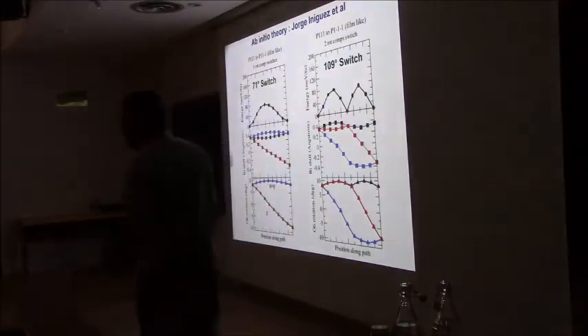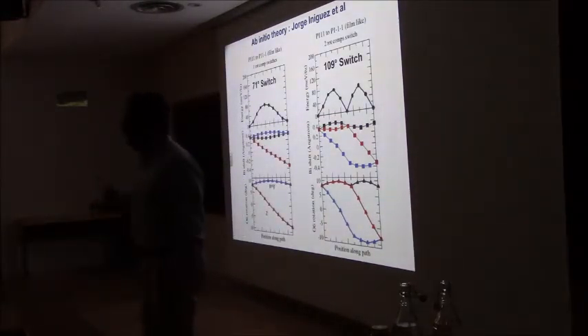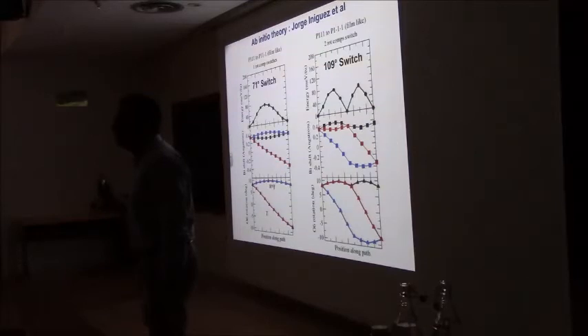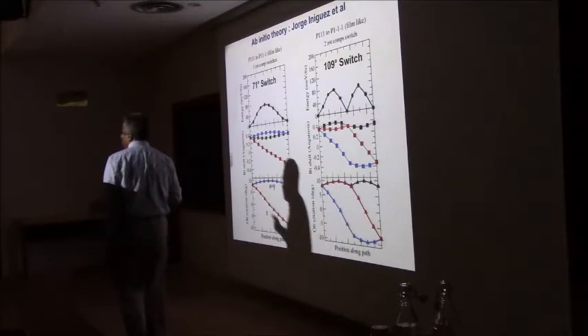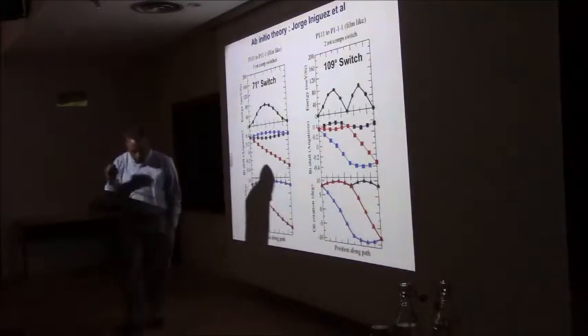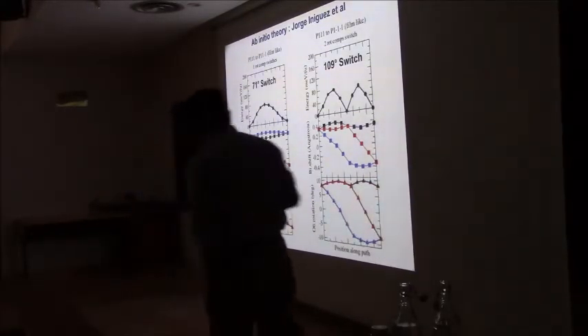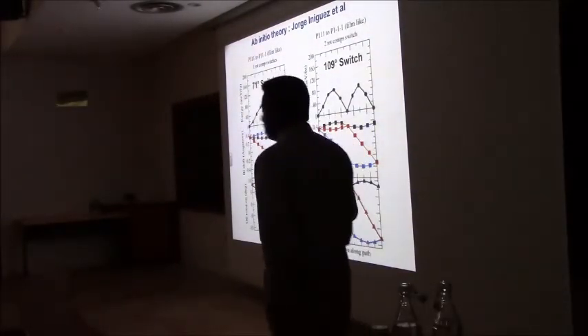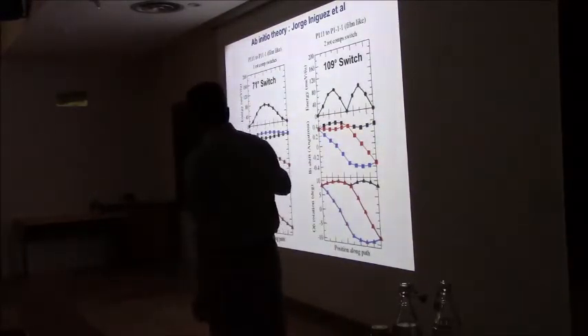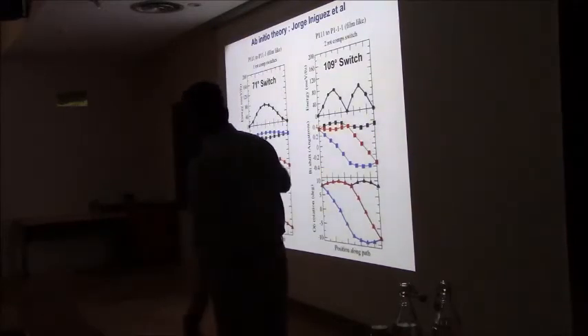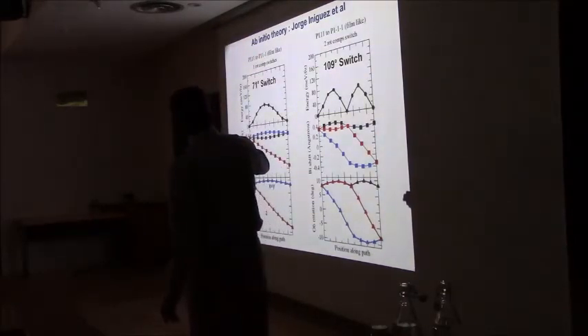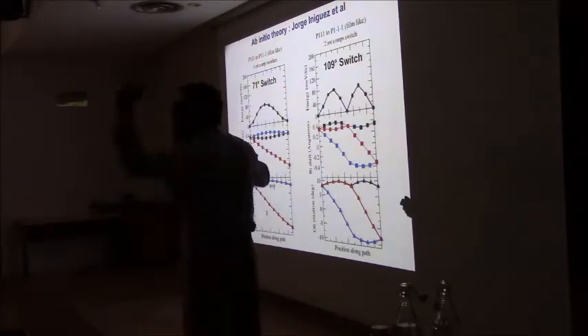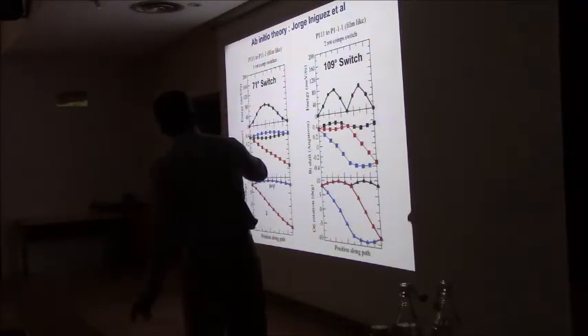Now, Jorge's, about 5-6 years ago, this is 2010, he said, maybe Nicola Spaldin and Claude Ederer missed something. He said what happens to the canted moment will depend very much on how I took this through the process. That's the other thing that we learned about bismuth ferrite, and we'll get back to it in just a second. I'm kind of stepping ahead of myself. So what did Jorge do? He basically took the crystal structure I showed you, and he said, let me do a 71-degree switch, which means I go from 111 polarization direction to 111 bar. That's a 71-degree rotation. And what he found was, that's the energetics of that.